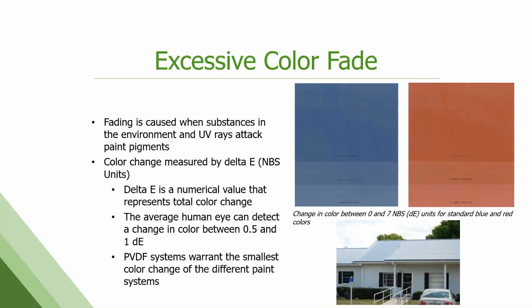The roof at the bottom is something we run into quite a bit. This is a situation where an installer mixed 2 different paint systems on a roof. So most of the roof was a polyester, but there were a few panels of higher end Kynar that got mixed in and used. So those have held up and not faded, but the rest of the roof has started to deteriorate. And it's not an uncommon thing where there's been a mix of products on a job site. So the panel manufacturers and the installers, that's on them to make sure that that doesn't happen.